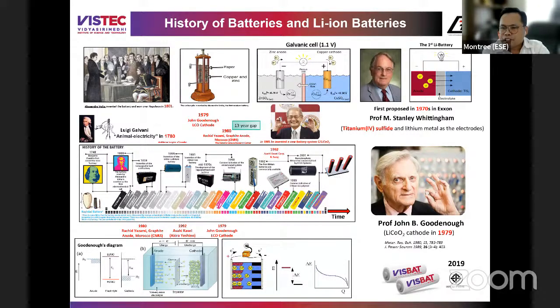When we are charging, the lithium from the cathode goes to the graphite anode. At the graphite, we have space between two adjacent graphene sheets. The space there can hold lithium when we do charging, and then the voltage difference between anode and cathode goes up to say 4.2 volt, for example. And then when we use the battery, the voltage reduces back to 3.0 volt, and then we recharge again.